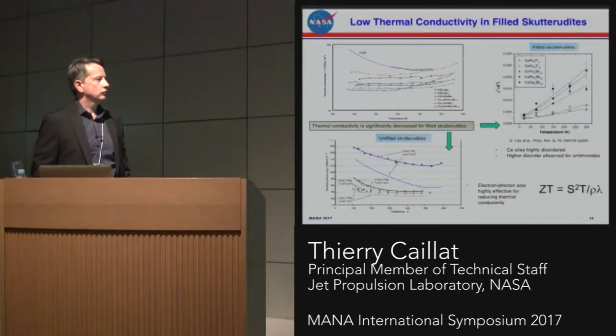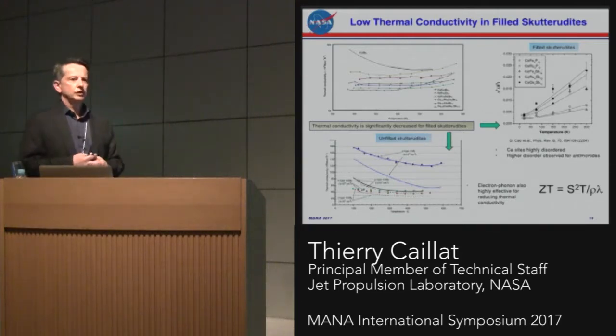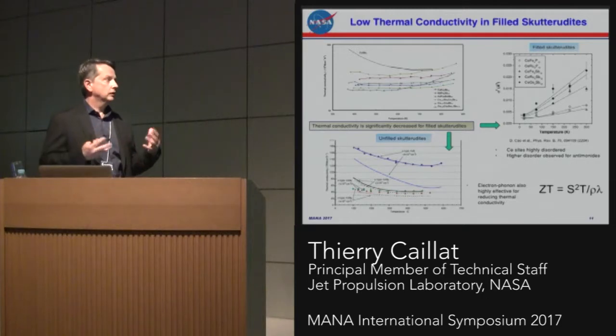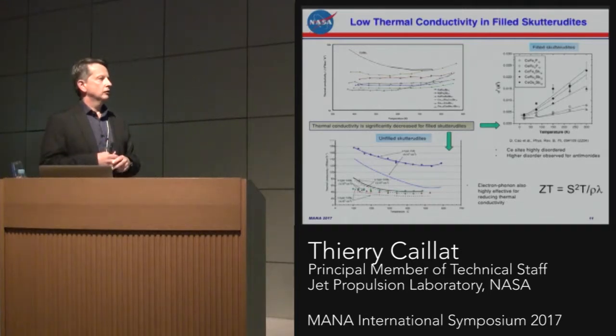So this is good. Going backwards here, one of the things going on in the community is the rattling of the rare earth inside the cage, the voids inside the structure. Is it really generating all that decrease in thermal conductivity? This is the unfilled skutterudite, cobalt triantimonide. If you do the rare earth filling, you get a substantial decrease in the thermal conductivity. If you look at the rattling amplitude of the cerium inside those materials, you see a pretty high temperature dependence. So the cerium sites are highly disordered, and they definitely contribute to the reduction of thermal conductivity that we are seeing.